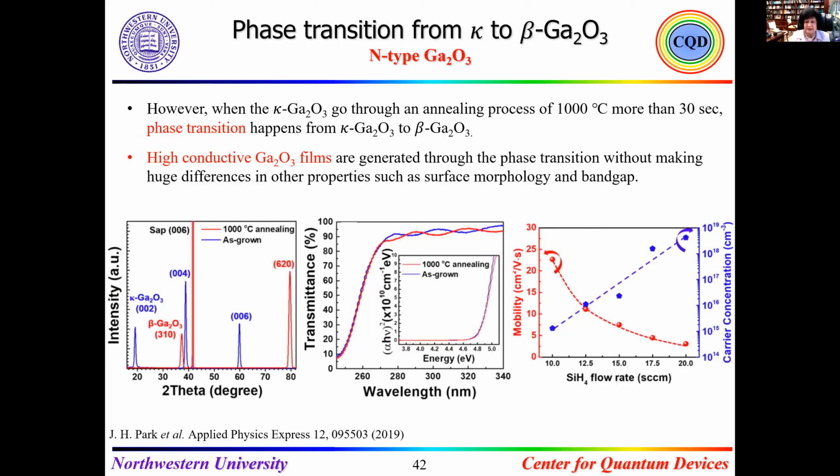But unfortunately, the material is very resistive. There is no way to make any measurement. We doped with silicon and with tin, and with the silicon, unfortunately, it was again resistive. So what we did, similar to aluminum nitride and aluminum gallium nitride, was to try annealing.